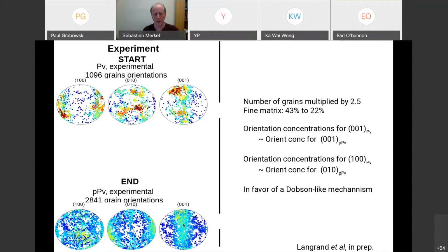And if you remember the mechanism that was suggested, it was a rotation around 001, so it makes sense, and it's compatible with those mechanisms. Now, if we look more carefully, it's not as easy to see, but the orientations of 100 in perovskite are not so far from the orientations of 010 in post-perovskite. And that matches what David Dobson suggested, not the other two.